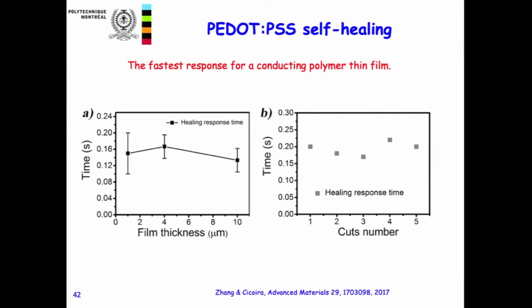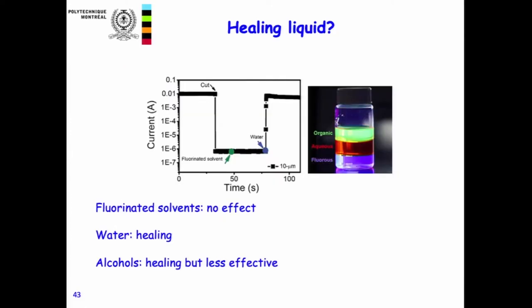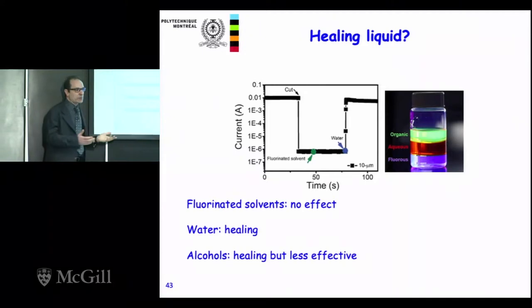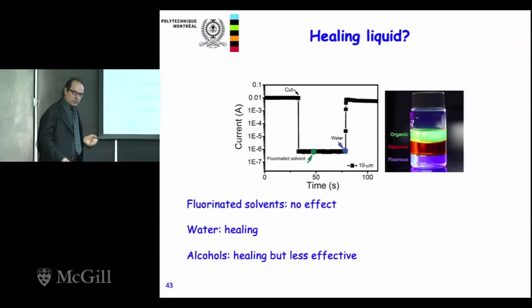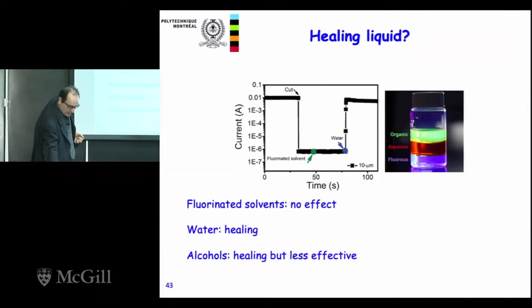Then what we did, we tried to use other liquids to heal the material. And the first one we had in mind is this fluorinated material we use for lithography. Naturally, you see here we cut, we put the fluorinated solvent, nothing happens. But then we put water on the same cut, and you recover the current. So water is needed to have this healing. We also observed something with the alcohols, but it's much less effective also because the alcohols we tried are much more volatile than water.